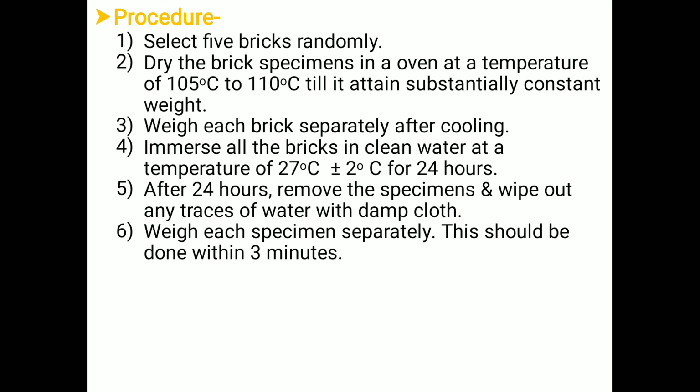And the fifth step is, after 24 hours, remove the specimen and wipe out any traces of water with a damp cloth. After removing those bricks from the water, we will wipe out the traces of water with the cloth. And the very last step is weighing each specimen separately. This should be done within 3 minutes. After wiping each and every brick, we have to weigh each brick separately, and that process has to be done within 3 minutes.